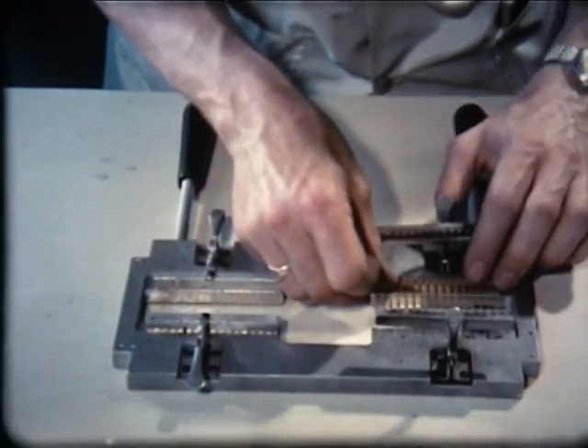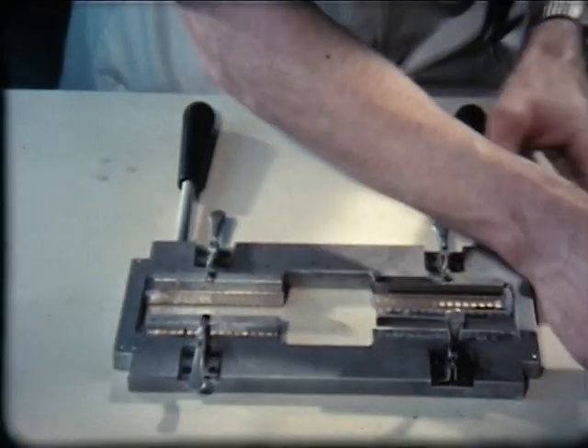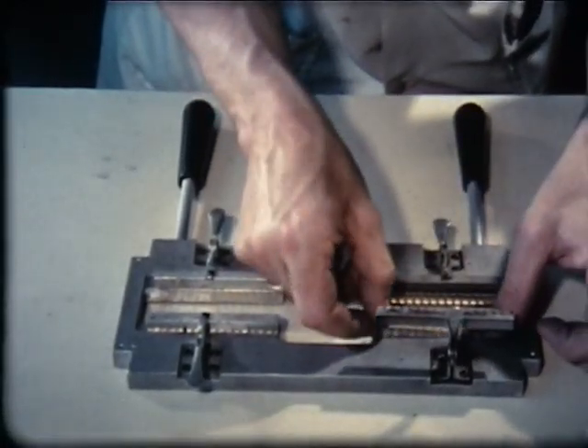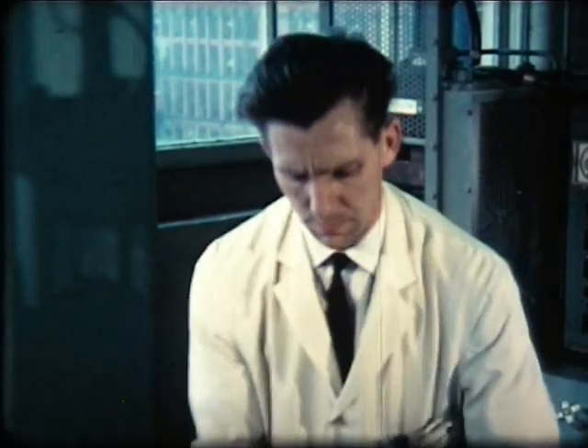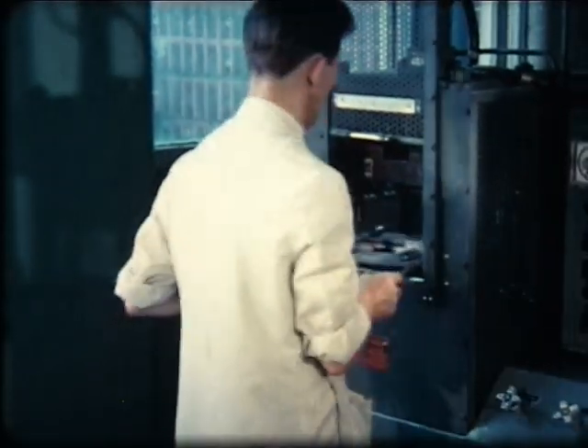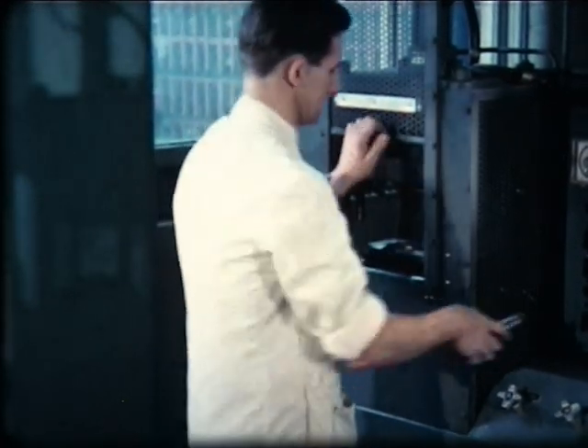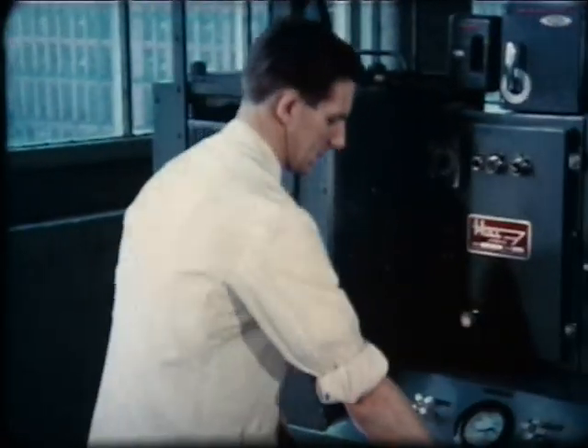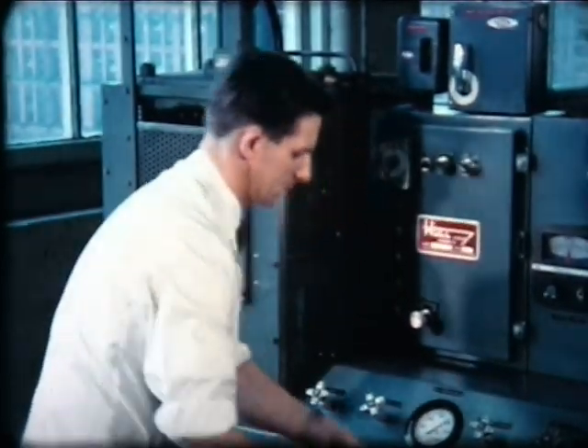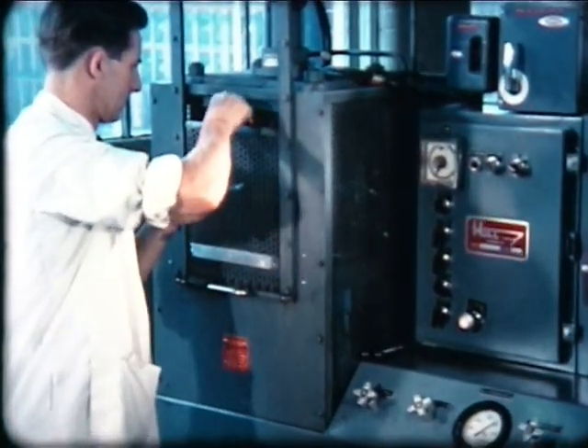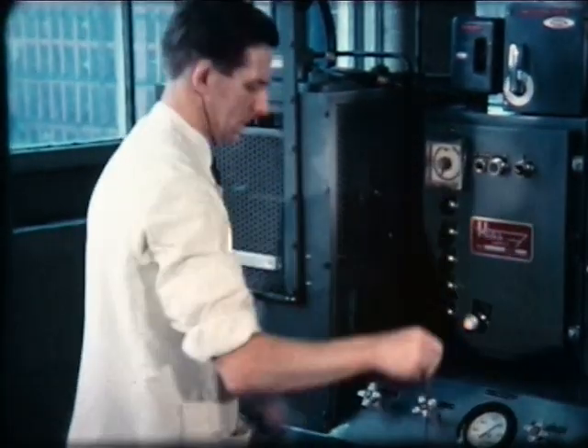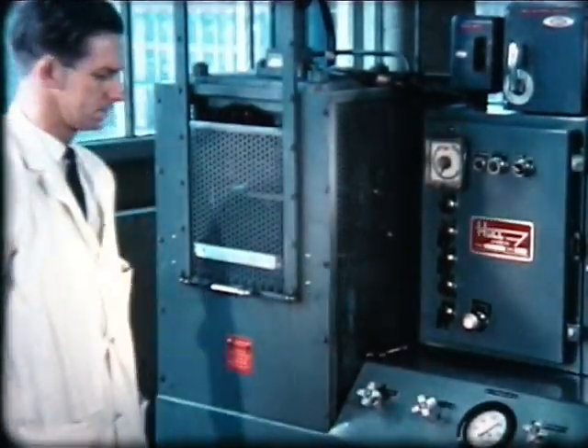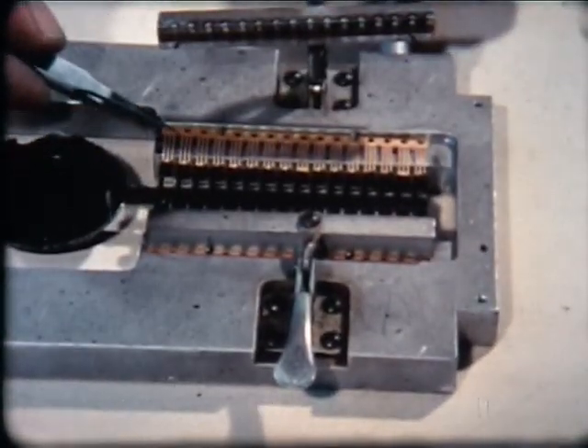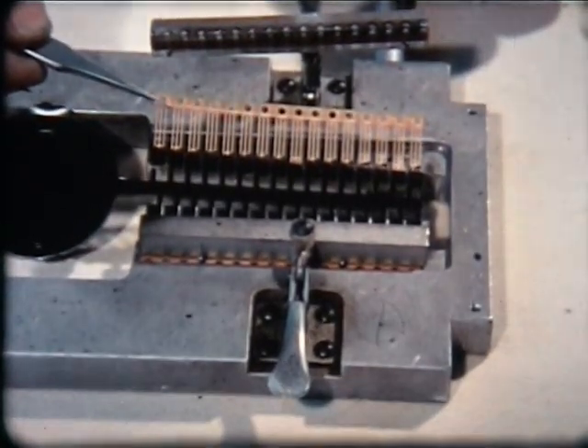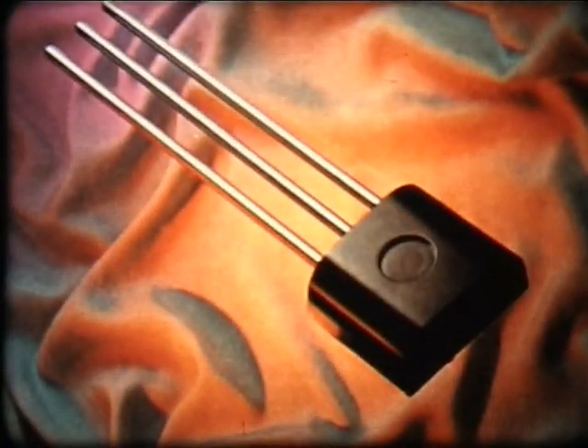For encapsulation, the frames are divided into subframes of 16 transistors, which are then loaded into a transfer molding machine. The epoxy resin used for encapsulation has been chosen with great care in the light of many years' experience in making resin-encapsulated diodes. The resin is first heated to about 150 degrees centigrade, which makes it as thin as water. Then it is forced into the mold under a pressure of 90 pounds to the square inch. This guarantees a free flow around the dice and lead wires, so that the structure becomes completely solid and mechanically very strong.